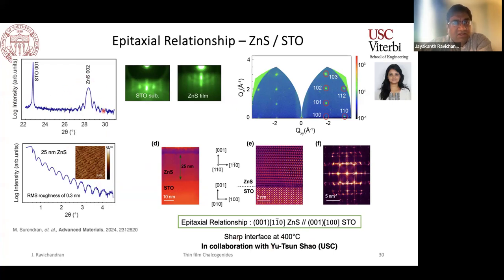This is a representative Bragg reflection where you can also see these Pendellösung oscillations and also Kiessig fringes in your reflectivity. We had some challenges in doing a standard reciprocal space mapping using our thin film diffraction system. So we used our small angle X-ray scattering, which was a much easier way to get all these reciprocal space maps, and we could get a little bit better sense of what sort of in-plane epitaxial relationships we have.